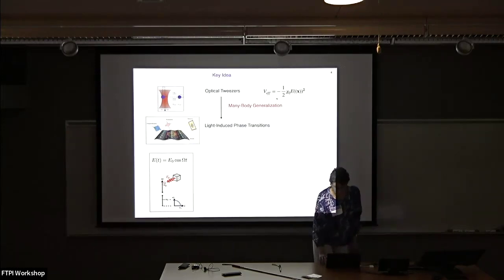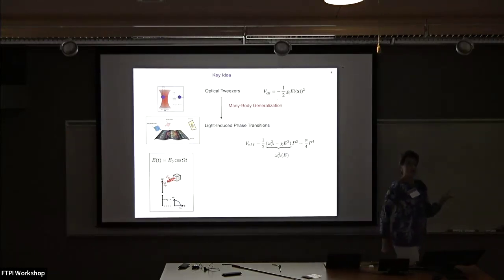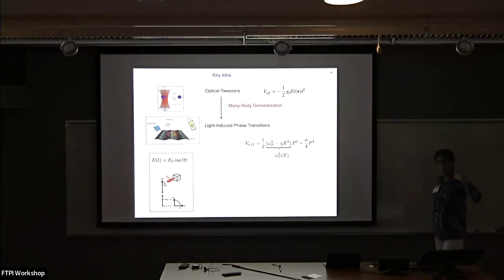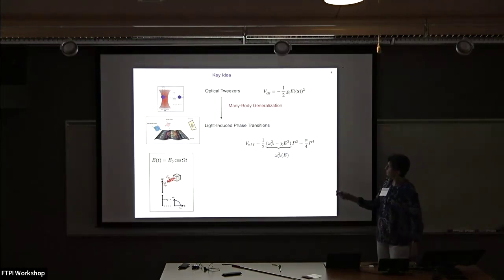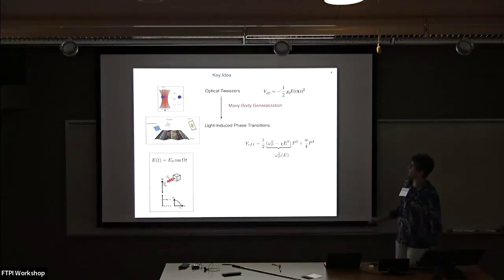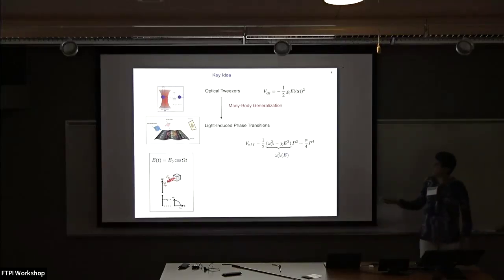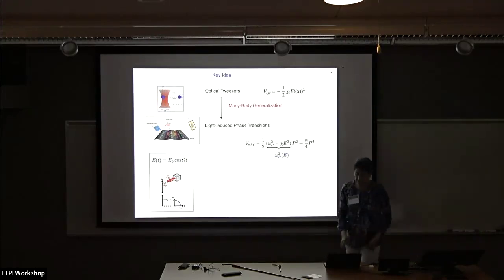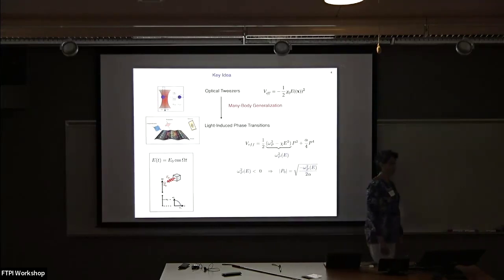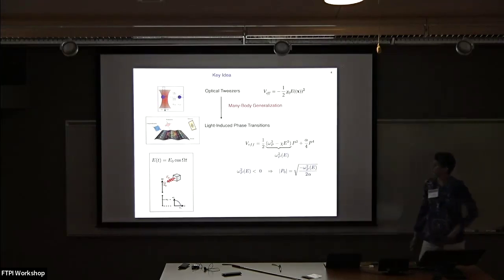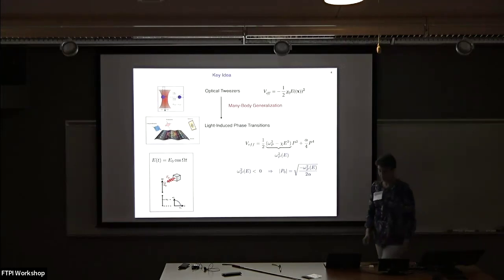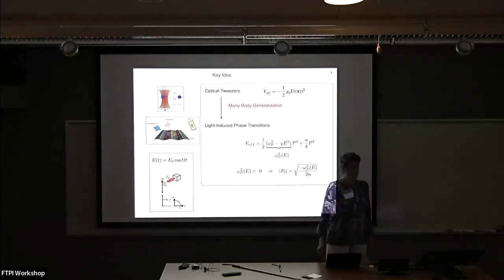You have an effective potential, and for example, if you have the anharmonic coupling, let's take Cavalleri's example, you have the anharmonic coupling to the high-frequency mode, and that high-frequency mode is resonantly pumped, then when we look at the effective potential, what happens is that we get a new term. This is the bare mass, and here we get a new term that's proportional to the fluence, E squared. And so we get a mass that's a function of the amplitude of the electric field. And eventually, because this comes in with the minus sign, the mass goes soft, and we get a polarization. Okay, so that's the key idea.